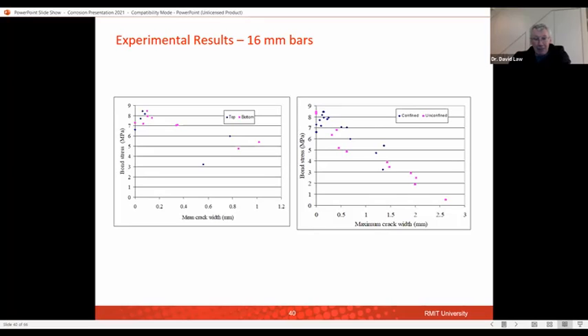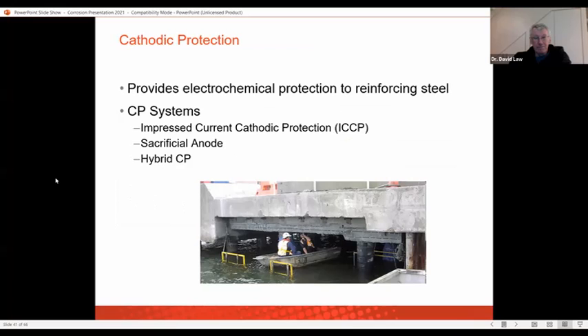You can see here, this was the mean crack width, and this was the maximum crack width. And again, the maximum crack width gave us a better relationship actually than a mean crack width on that deterioration. So there was a suggestion, and this is still again some ongoing research, but simply by being able to monitor and measure those crack widths, we will get an understanding as well as to how we're losing bond from the bars.